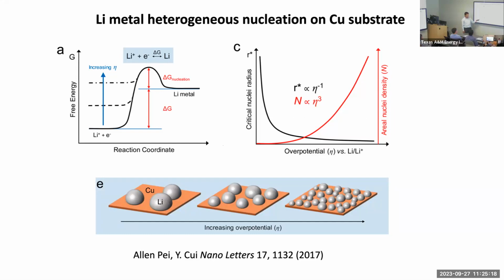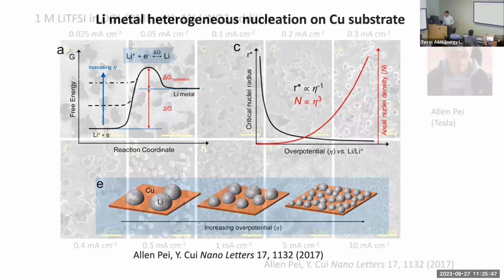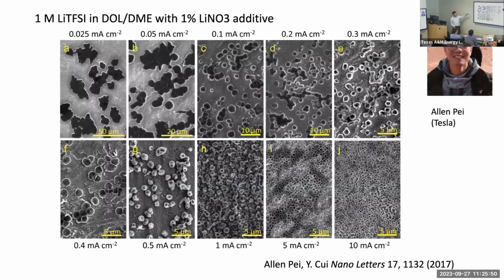Classical nucleation theory teaches us that if you increase the driving force of nucleation, the size of the nuclei diameter becomes smaller, but the number density is a lot more. It's the scaling rule: the radius versus the overall potential, the driving force of nucleation, is 1 over eta. But the number density is the cubic function of eta. So, looking at this, we were able to use different current densities for deposition. The higher the current density, this number per centimeter squared, the more driving force.